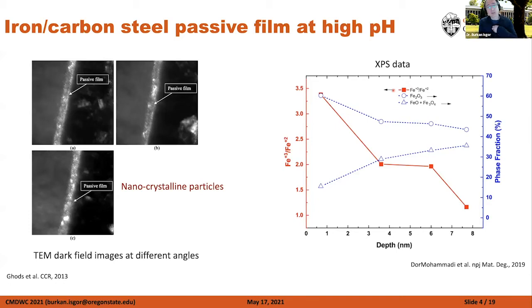And if you look at the XPS data, XPS is not done on those FIB samples that I mentioned, but on regular steel or iron surface. We have done both. You basically create a pristine surface, develop the passive film again, take the sample into an XPS, and then do XPS analysis. The horizontal axis here is the depth, which means that this end, which is 0, is the exposed surface of the passive film, and this end is the actual interface between the steel and the passive film. You can see that the red line clearly shows that the inner part, which is the interface between the iron and the oxide film or the passive film, has a Fe3 to Fe2 ratio of about 1.